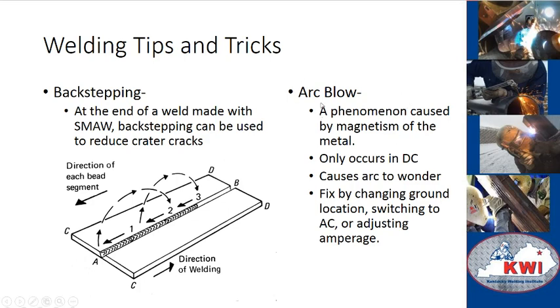Arc blow is a crazy phenomenon that is caused by the magnetism of DC welders. It only occurs on the DC side. Basically what happens is it honestly feels like you have no flux on your electrode. Your arc wanders. It goes kind of crazy. It deflects. It typically happens because those magnetic force fields are concentrated in the corners of the weld. And they say, what do you do to fix it?